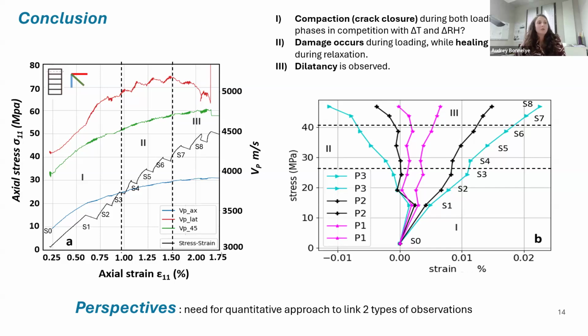So far there is nothing brand new, in the sense that we're putting together some pictures that show the full field together with the evolution of P-wave, but we're not very far from a quantitative approach that will link the variation of P-wave with a quantitative way to discriminate all of the different mechanisms of deformation that are taking place. So we hope to be able to link a percentage of increase in P-wave velocity with a percentage of compaction, and most of all, a percentage of damage that is generated, in order to understand when we will reach the critical point where the deformation is going to properly localize and make the sample fail